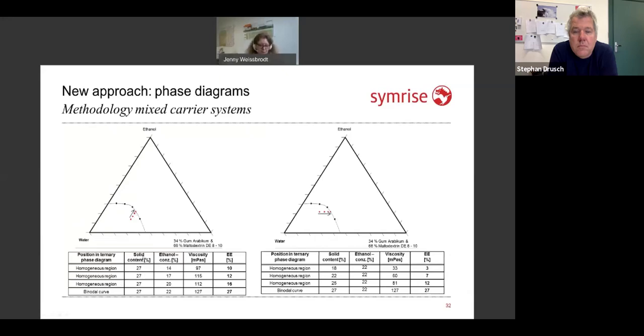We kept the solid content in the first diagram constant. We increased the ethanol concentration, and what we found out is that the encapsulation efficiency goes up too. Does it work in the other direction too, if we keep the ethanol concentration constant and then just increase the solid content? We did this too, and even here we could observe that the encapsulation efficiency was improved.